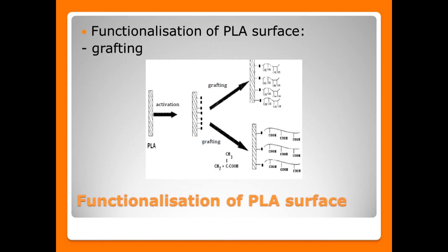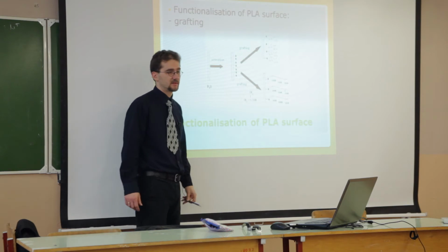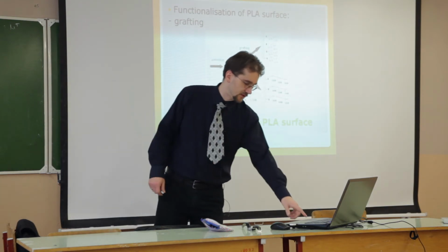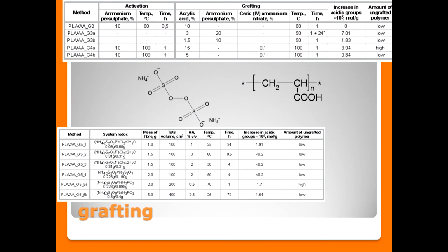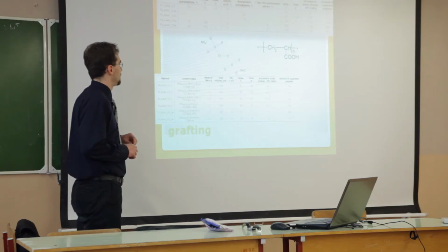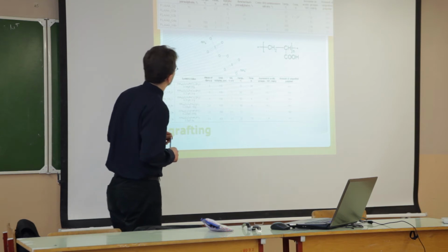In the first slide, I showed you how we can attach polyacrylic acid to the surface using a grafting process. Ammonium persulfate was used in these processes for initialization.